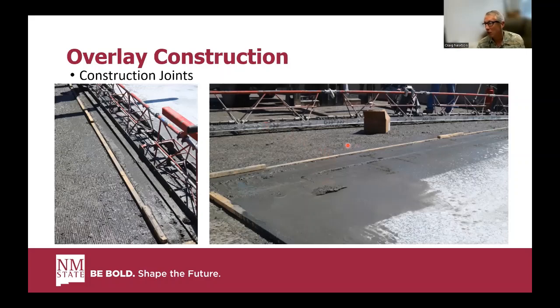In this case, there was no plan for where to put it once we realized that the contractor just didn't have enough material to finish the eastbound lane on the first placement. So it was a discussion on the job site to choose: do you want it above the support in a negative moment region where the joint's going to open? Do you want it in a positive moment region where it should have some compression? Or do you want it just a few feet off of the pile cap so that you can have it near an inflection point? In the end, we chose something near the inflection point, just to try to make it stress neutral.